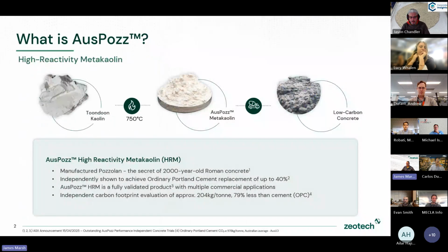So I'm guessing most of you know what metakaolin is, so I won't dwell too long on this. From a basic standpoint, all we do is convert kaolin to metakaolin. It's a heating process at about 750 degrees centigrade, so it goes from a fully crystalline material, hydrous kaolin, and then it becomes, some people call it amorphous, but it's not truly amorphous. It's a semi-crystalline form called a defect spinel form of kaolin, which is known as metakaolin, and this is reactive. If you calcine it too hot, then you go to a fully amorphous material that won't react.